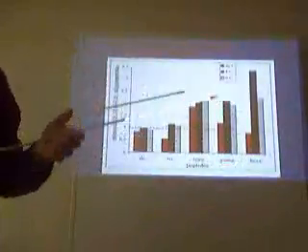And then we tried to understand why that is. We could measure the coherence length of these clusters, and it was very small. This is what we pointed out: it is only 15 to 30 nanometers when they undergo spontaneous resolution.